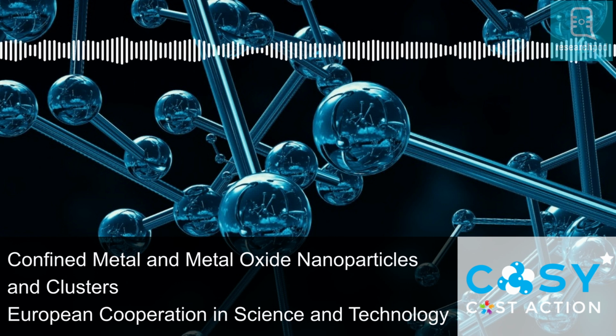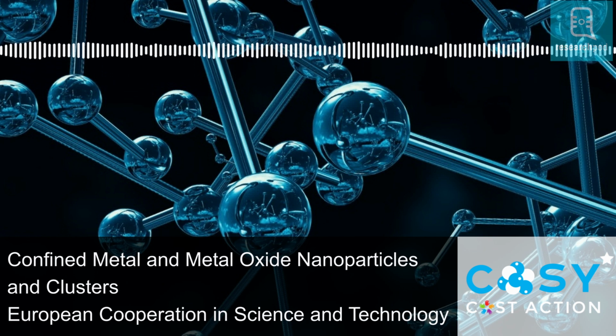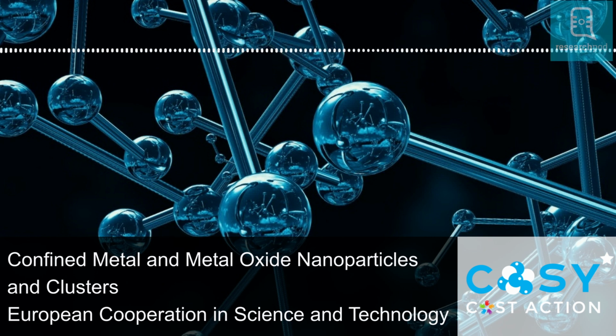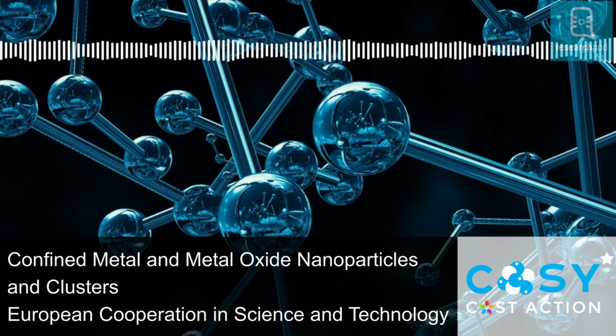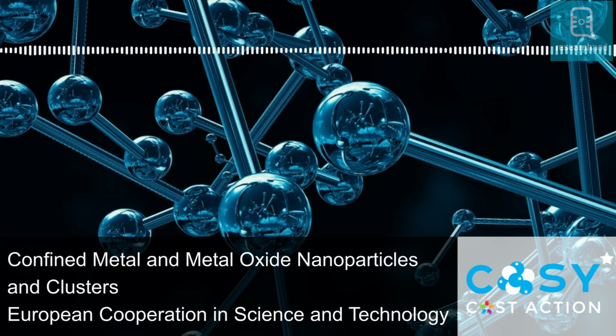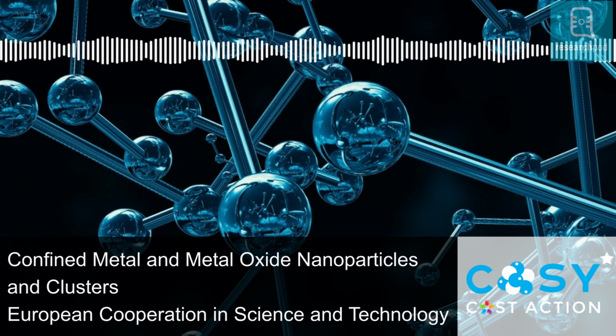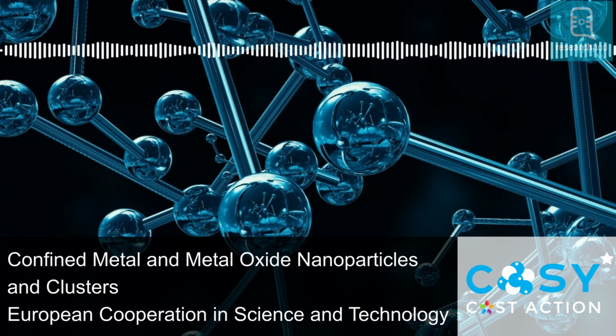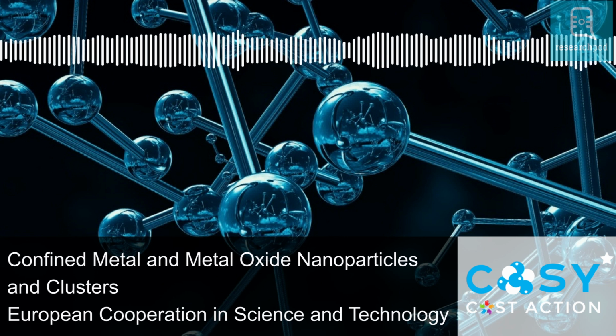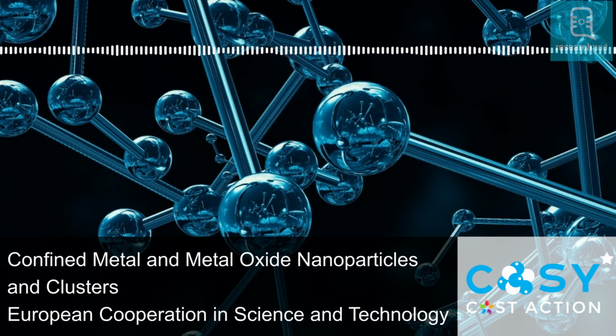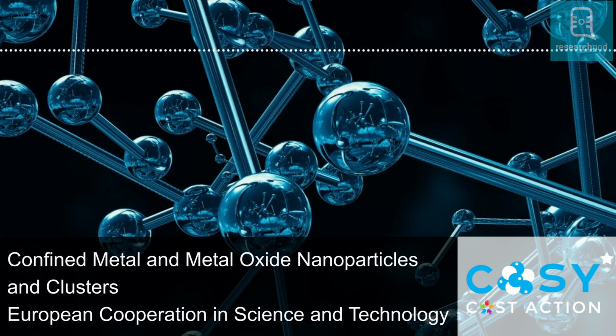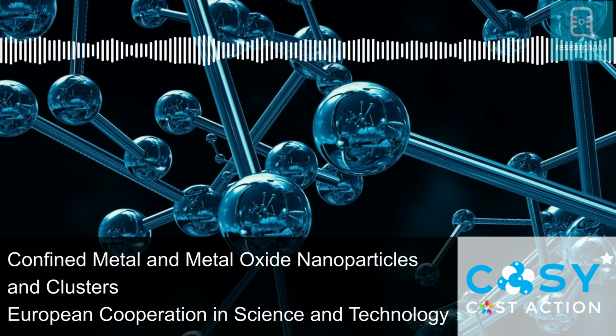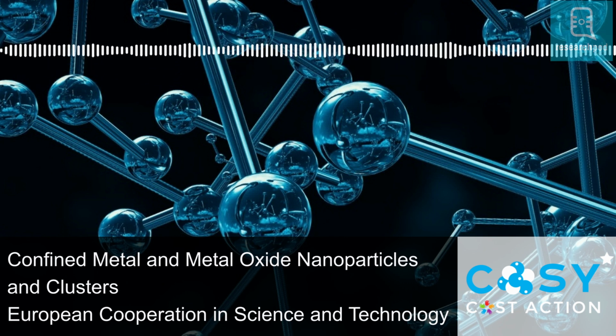Researchers applied the copper 5 clusters to a base, or support material, known as a substrate, of HOPG, that is, highly oriented pyrolytic graphite. They then performed spectroscopic experimental studies, and were surprised to discover the copper 5 clusters resisted what is known as irreversible oxidation, up to temperatures of about 500 degrees Celsius. The key point here is they discovered that copper 5 clusters can undergo some level of oxidation when exposed to oxygen, but they resist forming oxides that are stable or persistent. To complement the experimental findings, the group also developed advanced theoretical models.